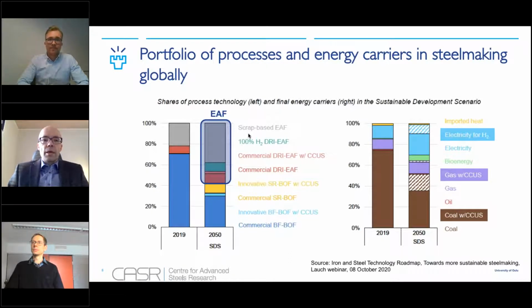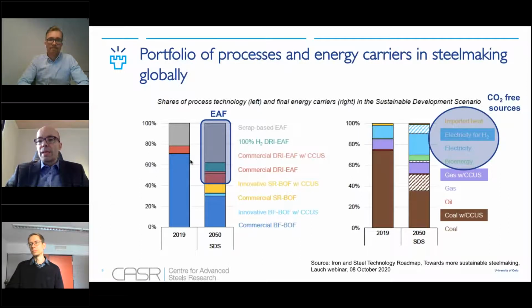Okay, good. So in the future, scrap as a raw material will be very important, of course, but there will be also an increased amount of 100% hydrogen-reduced direct reduced iron used as raw material as well, and then these commercial DRIs using natural gas with and without carbon capture and utilization together, so they form approximately 60% of the production in this scenario. And we can see that low or CO2-free energy will be very important to achieve these low carbon targets.